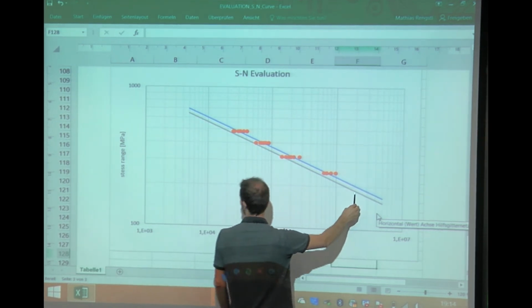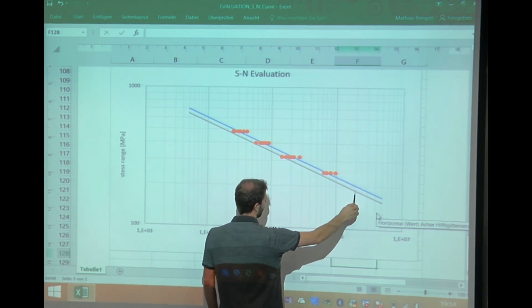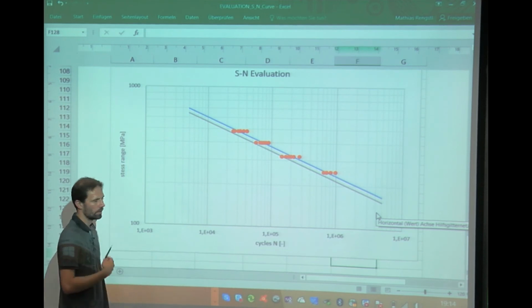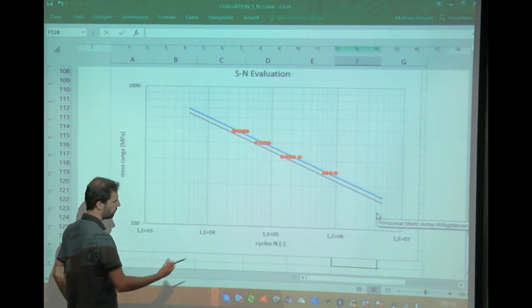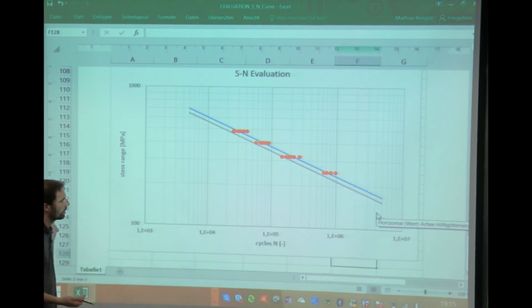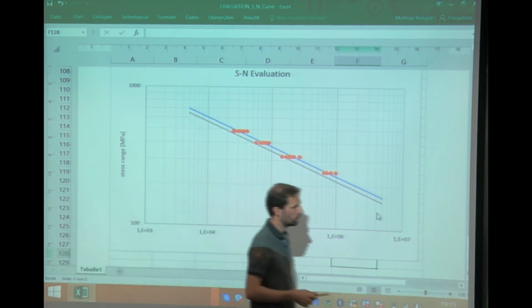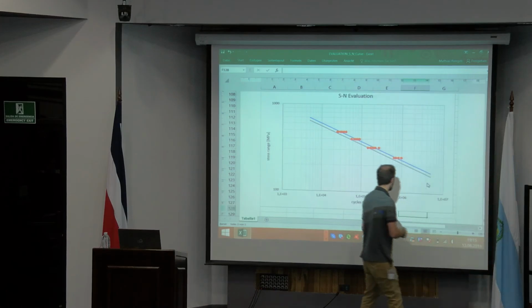And at this point, at the end, you can get the information about the stresses. And this is at the end according to a specific stress ratio, which you have applied during the testing. The notch stress, which is according to your model, specific to the tested detail.